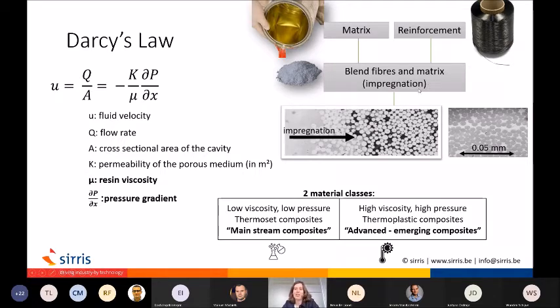This is called impregnation. So here you see a cross section of the composite. So you have here a fiber bundle, and we want the resin, which is before processing. Before processing, we have the two constituents which are separate. We want to blend them well. So that means that you have a resin here at this side, and you basically want to push this resin inside of your fiber bundle so that you don't have any porosity at the end of your process. So during the process, you still have porosity. As you can see, these are the black spots. We want to end up with a composite that is very well impregnated.